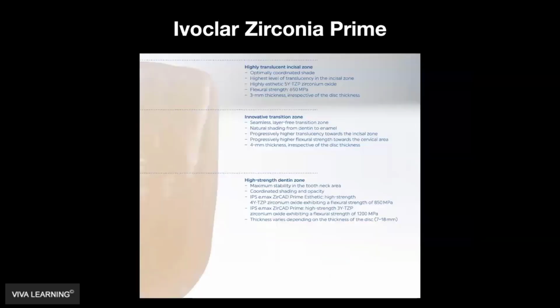But the little thing that I thought was misleading here, and you have to look at it, is they only have 3 zones. They have the highly translucent zone, and then they have the high strength zone in the dentin or the coronal part of the tooth, the translucent zone, and the incisal. The incisal zone is 5Y zirconia. So it is very aesthetic, but when you go to 5Y, you start to lose the strength. So it's 650 megapascals in the incisal zone. When we go down to the coronal part of the tooth, that is more of a 4Y or 3Y strength, and you can get a really strong zirconia, but it's only strong in the coronal part of up to 850 to 1200 megapascals in that coronal zone.